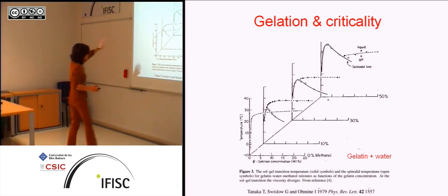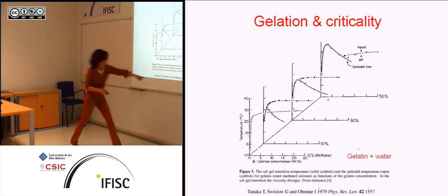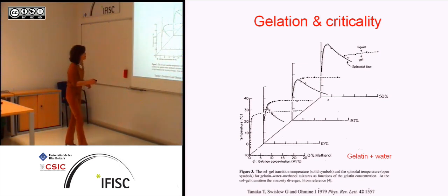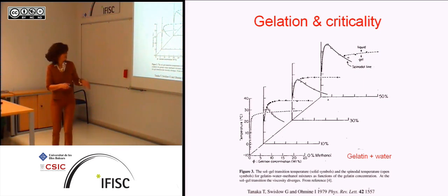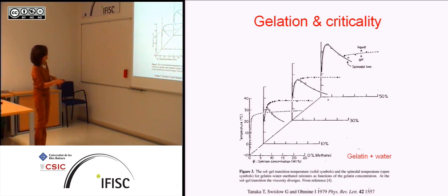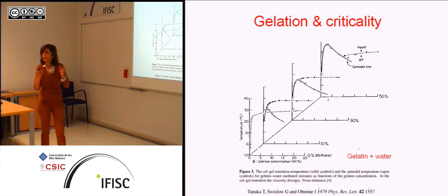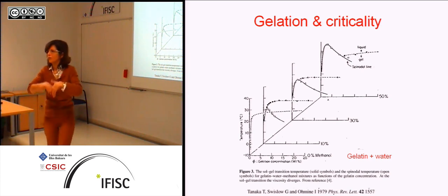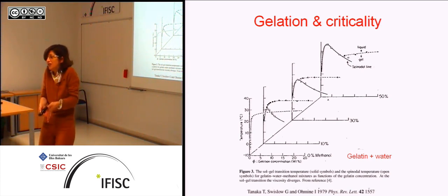It's also clear from experiments, I'm going back and forth, but this is one of the systems from the 80s, I think, 79, okay? So this is from the 80s, and this is just gelatin and water, and there's only a gelation or percolation transition here. But now if you start putting some alcohol, the water and the alcohol will phase separate, the percolation is still there, or the gel forming, and gelatin is still there.